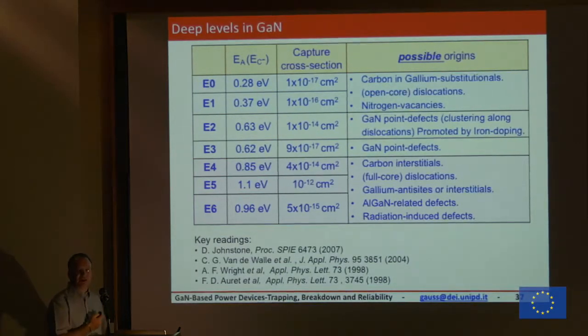With this, we identified, for instance, traps related to carbon, the one that you need to compensate your buffer. I can tell you, 99% of the trapping today in gallium nitride devices is related to the carbon that you need to have there, as I told you before, to have a good insulating layer, but it is also a site of trapping. So you see a lot of carbon, but also GaN point defects. What was Elke speaking about yesterday? Our material is not perfect. There is a lot of defects. We have gallium vacancies, we have dislocations, whatever. These are sites of trapping.